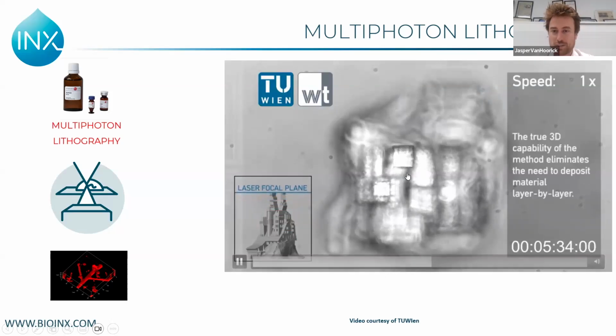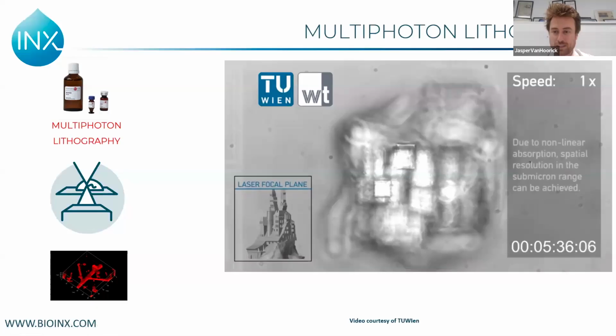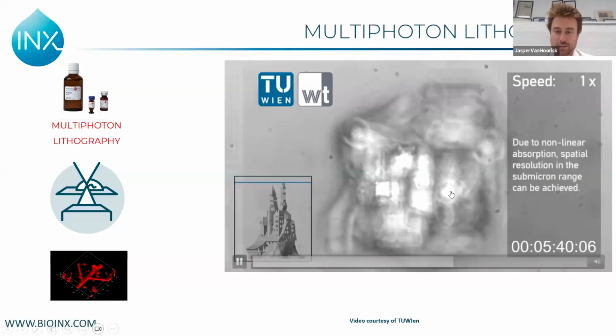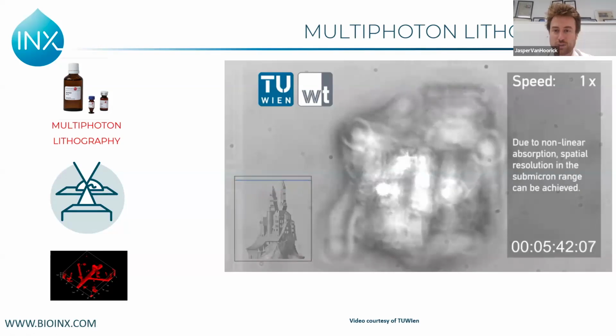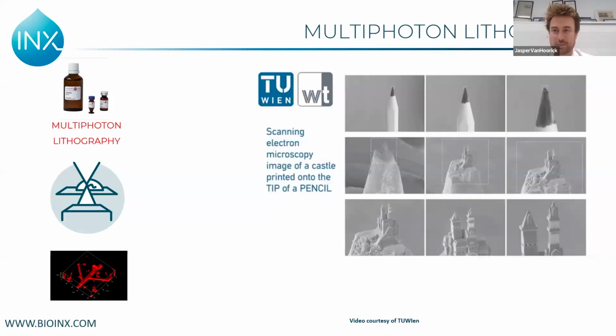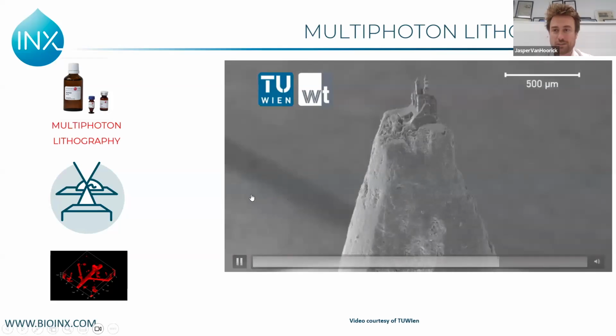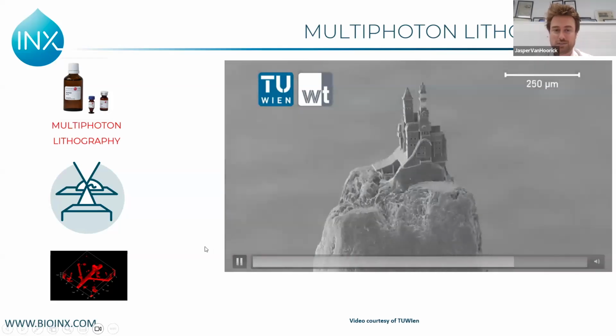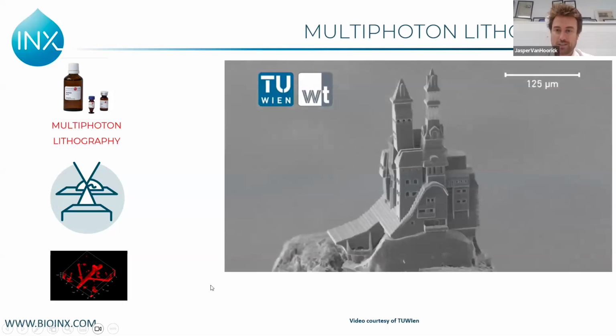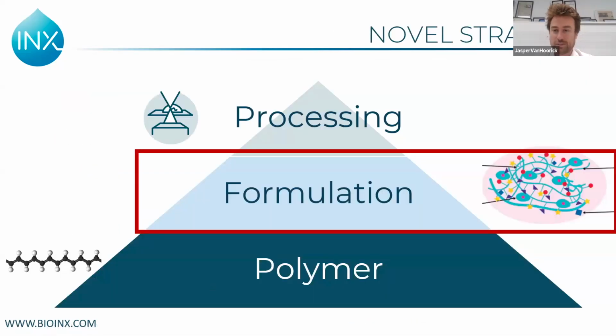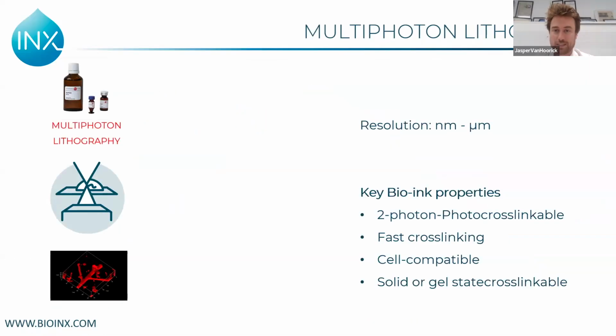Of course, there's no scale bar here, but in a moment you will see how tremendous the resolution is, because if you look where the castle is printed, the castle is actually printed on top of a pencil tip. So you can see that with this technology, you can go to extreme high resolutions, down to microns, tens of microns, and even hundreds of nanometers, which is of course very interesting from a bioprinting perspective.